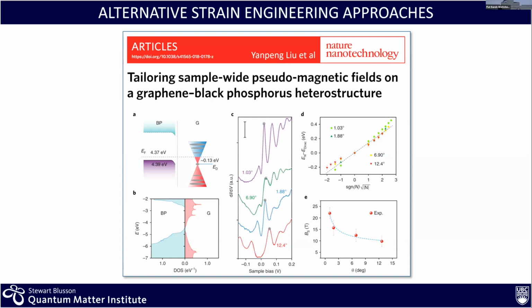The difference here is that we only see the levels above the zero point and not so much below the zero point, while in the STM you can actually see them. Our interpretation is that the spectral function is broadened very strongly as we go below the zero point. And so presumably that's why we are not able to see these features, which are weak to start with even above the zero point.